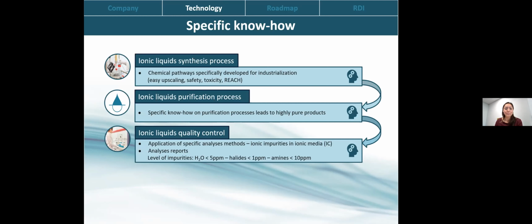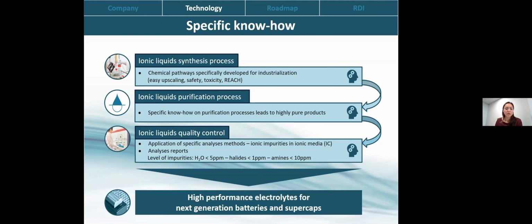So we have special modified analysis methods that can detect ionic impurities in ionic media, because ionic liquids are a very different class of chemicals. They are different from carbonates, different from other chemicals. So to detect them correctly, we have to adapt the analysis methods to find out the impurities level. Today we can achieve impurity levels down to less than 5 ppm of water, less than 1 ppm of halides, and less than 10 ppm of amines. So this leads to very high performance electrolytes for batteries and supercaps.